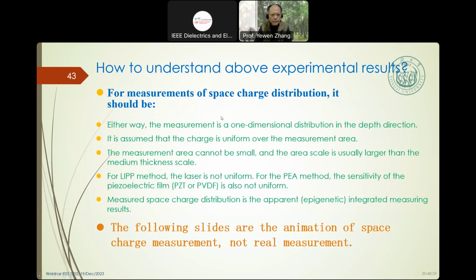So for the measurement of space charge distribution, it should be either way, no any method. The measurement at the one-dimensional distribution in the depth direction. It assumes the charge injection, the charge is uniform over the measurement area. This is a condition. The measurement area cannot be small, and the area scale is usually larger than the medium